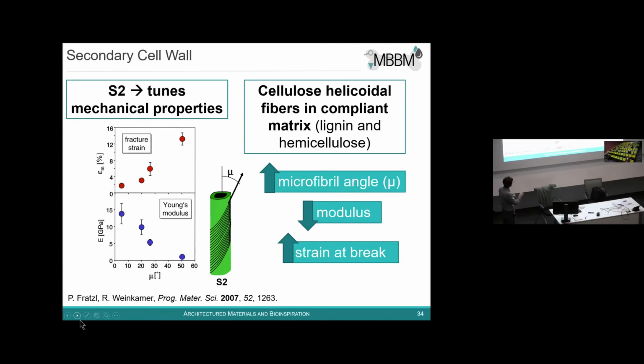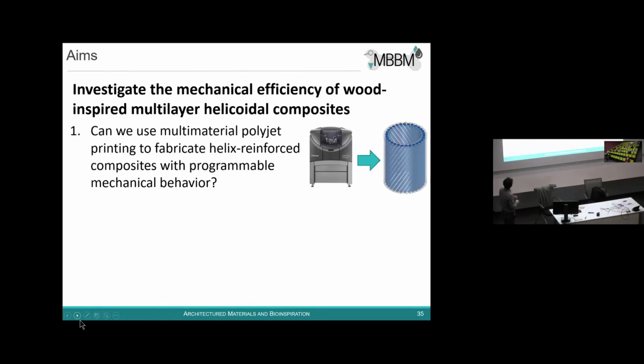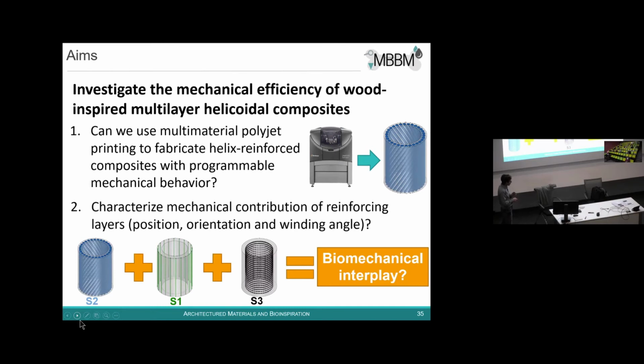So if you have angles which are very small, you have vertical fibers, and your wood is very stiff, but it's also very brittle. So the fracture strain is very small. And when you increase this angle, you decrease the stiffness, the Young modulus, but you increase the fracture strain. So the wood cell wall behaves like a spring. And this is done by tuning the angle of these molecules. And our idea is to translate this, which is quite straightforward, into artificial materials with 3D printing. And then we want to exploit it, which is a little bit less straightforward.